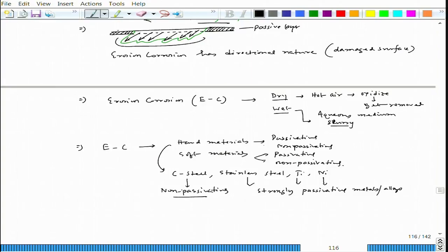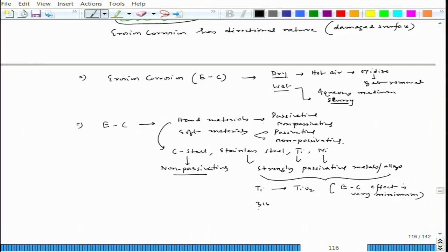So non-passivating. Now out of that, if we consider the passivating kind of metal, they depend on the passive layer strength, okay, that erosion corrosion factor can be highly felt or it can also be reduced. For example, in case of titanium, it has titanium oxide, which is a very, very adherent, strong passive layer. So in case of titanium, the EC effect is very minimal, very minimum. But stainless steel, let us say 316 or 304, 316 contains molybdenum, molybdenum increases EC resistance,